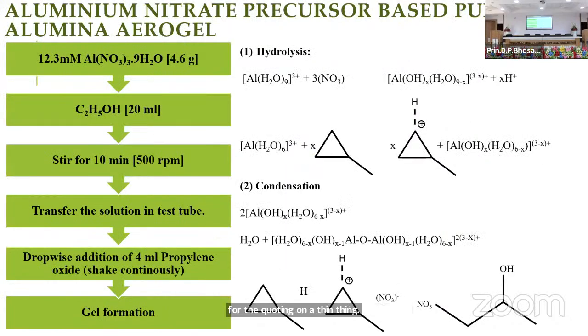Furthermore, there are two other precursors, aluminum chloride and aluminum nitrate, and the chemical reaction is presented here. Here we use propylene oxide for the solution of aluminum nitrate. The propylene oxide acts as an agent on the aluminum nitrate precursor, and then the Al-O-Al bridge forms, as we can see in the condensation reaction. After the condensation reaction, before gel formation, we further use the dip coating technique for the alumina thin film formation.